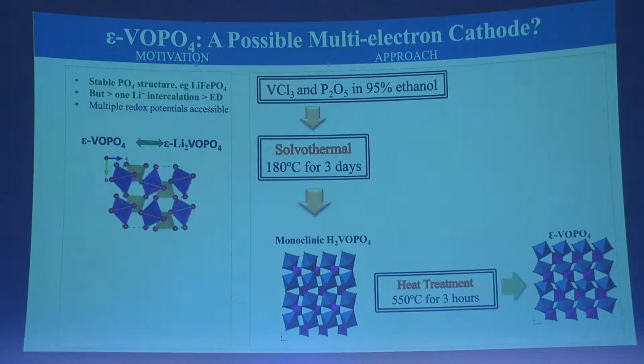So what is this material? It's a nice tunnel structure. It's better than lithium iron phosphate. Lithium iron phosphate is one-dimensional tunnels. These are 3-dimensionals. And you can see the lattice there. The challenge was, can we make this material in a form that's electrochemically active? Remember, phosphates are inherently great insulators, so you can't get electrons in and out. So we had to make them small enough and get them in.